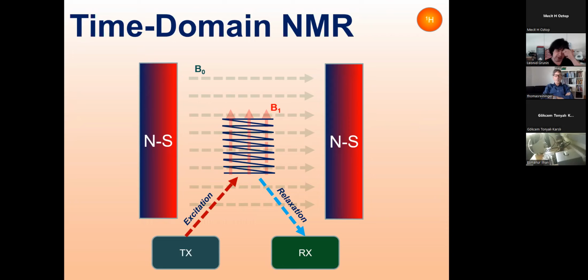When we talk about time domain, the machine for time domain NMR is normally much simpler than for high resolution NMR. That's why it's more affordable for universities and for industry. The basic component of this machine is the magnet. Here I show it like 2 poles of the magnet. The magnet produces the external magnetic field, which we call B0, and then we need to put the sample somewhere, and we use a radio frequency coil. We put the sample inside the coil, and then we do excitation. The machine produces a strong magnetic field perpendicular to the main magnetic field, and this field causes spin transitions. After we excite, the system relaxes. This process is called relaxation, and we detect it through the receiver. So in all time domain NMR machines, there must be a magnet, the probe, which contains the coil, a transmitter that excites, and a receiver that gets messages from spins about the structure of samples.